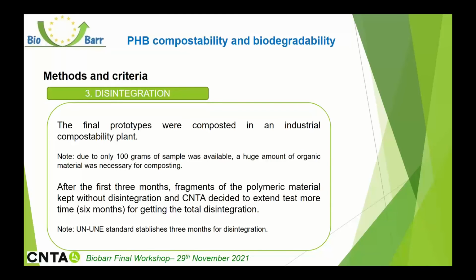Regarding compostability, according to the UNE standard, 3 months would be enough for getting total disintegration of the samples. However, after these 3 months, we observed some big fragments of the polymer material without disintegration, especially in the metallized sample. And we decided to extend the test 3 months more, because what we wanted to observe is the disintegration capacity of the samples.